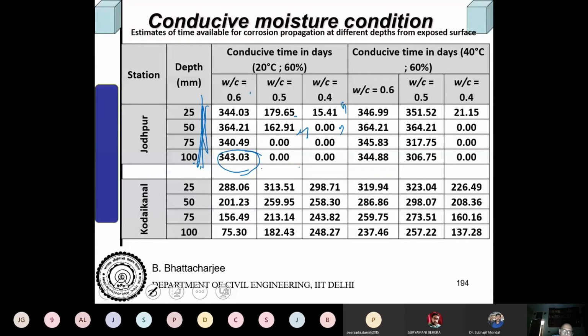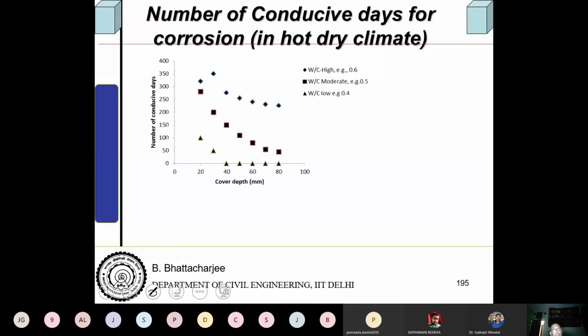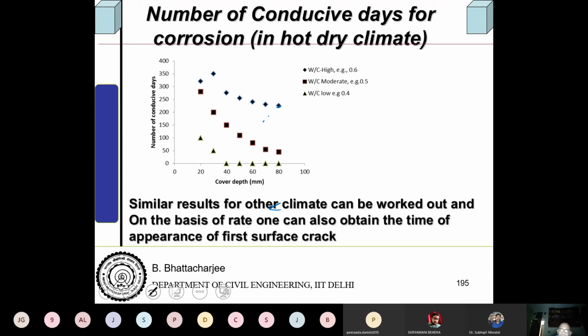This is in Jodhpur, but in Kodaikanal again you can find out and so on. So one can obtain this for corrosion, for various climatic conditions. So cover depth for high water cement ratio in hot dry climate, this is Jodhpur. That's again obtained. So if your cover depth increases, water cement ratio is 0.6, number of conducive days where corrosion would occur, full year it is not going to occur. Only some part of the year it will occur. Similar results for other cities actually have been worked out, some of them.